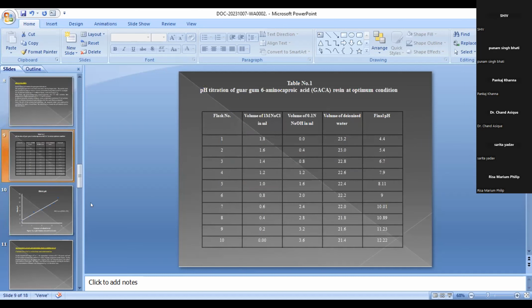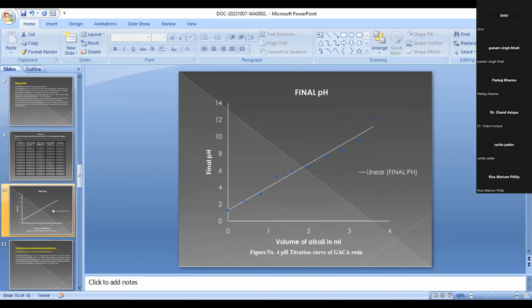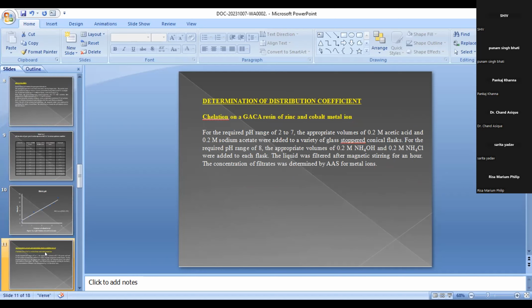These tables are given below, and the next is the graph plotted between the final pH and the volume of alkali in the solution. Next is the determination of the distribution coefficient of the resins and cobalt metal ions. Appropriate volumes of 0.2 M sodium acetate were added to a variety of conical flasks for the required pH range. The appropriate volume of 0.2 M NH4OH and 0.2 M NH4Cl were added to each flask. The liquid was filtered after magnetic stirring, and the concentration of the filtrate was determined by AAS of the metal ions.